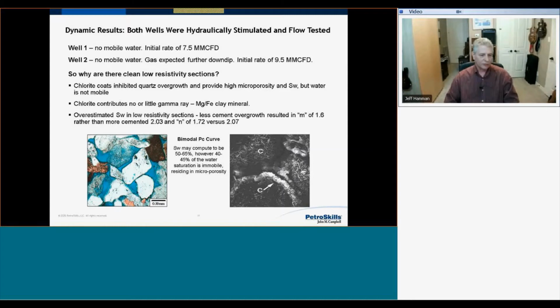And we see a similar effect with N in the clay coats because we have a continuous microporosity filled with conductive brine. The N then is only 1.72, and in the more cemented section, it's 2.07. So again, if we assumed M and N of 2, we're not too far off in the cemented, but we greatly overestimated the volume of water in the clay-coated section. We may compute a water saturation of 50 or 60%. However, where we have these clay coats, 40 to 45% of that water would be immobile and reside in the microporosity. So we overcalculated the water saturation, and most of the water saturation that existed is actually tied up in microporosity and not mobile, and that's why we didn't cut any water on completion.